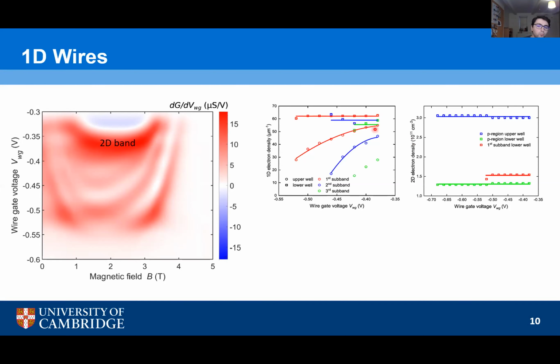On the other hand, on the top well, you see the 1D density. By varying the gate voltage, you can change both the 1D density in each subband as well as progressively occupy more subbands. So you can go from 1 to 2 to 3, or you can pinch off the wires if you want. So just to summarize, we observe multiple 1D subbands, anywhere from 3 to 4 for these devices.